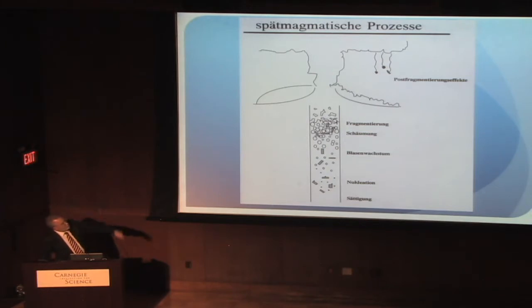What I have here is a simple one-dimensional plot that we don't really believe in anymore, but it helps us to strip out the processes one from another so that we can investigate them individually and then in chain reactions in our experiments. At the bottom I have saturation in German, nucleation, growth of bubbles, foaming of the system, very important because foams have rigidity, solid-like behavior, they have elastic moduli, they have a shear modulus, and therefore they will resist deformation by elastic response. That's why your foam stays on your bathtub in a transient, rigid state for a long time.